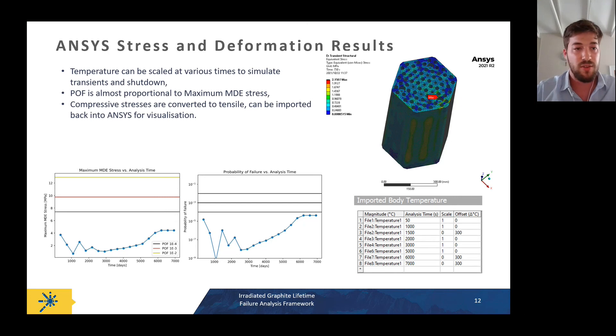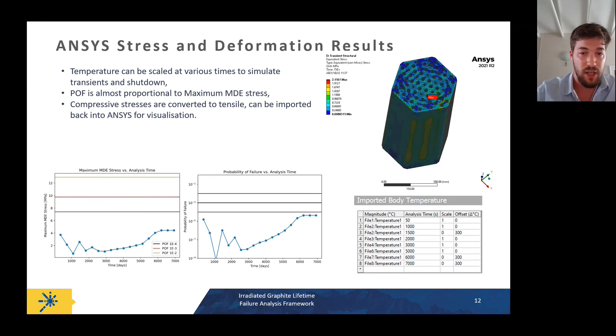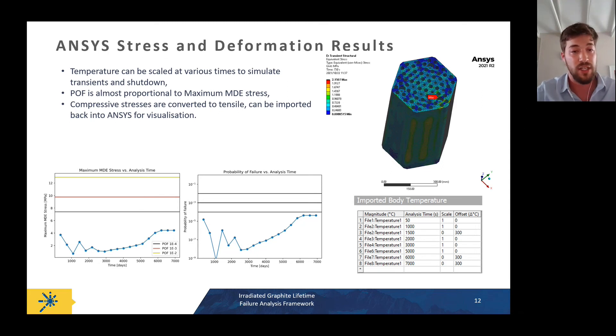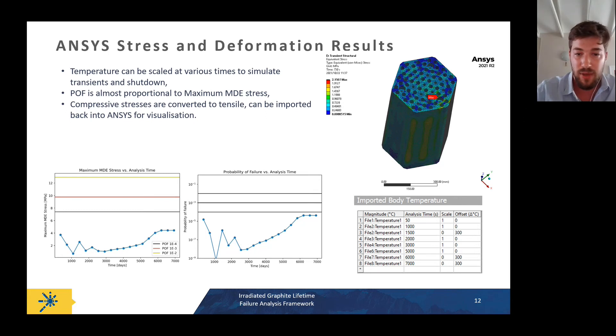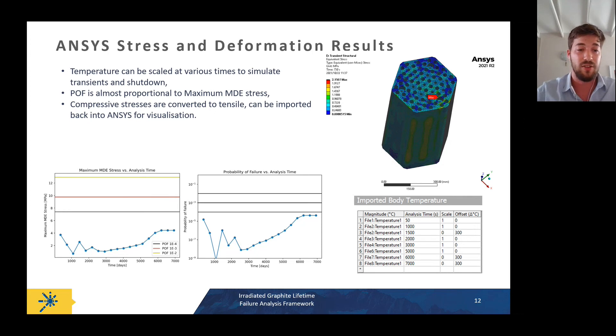Looking at generic results for maximum stress in a single block over its lifetime, the highest stresses typically occur at beginning of life due to thermal stresses. As more neutrons irradiate the blocks, stresses creep out and slowly decrease. However, dimensional change eventually becomes dominant and stresses gradually increase again. The spikes visible in the stress curves represent simulated shutdowns — temperatures were changed to a flat 300 to simulate extended shutdown periods, and then ramped back to normal, allowing simulation of multiple shutdown events throughout life.